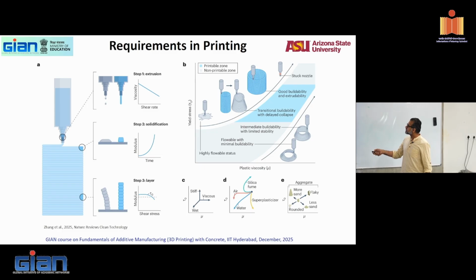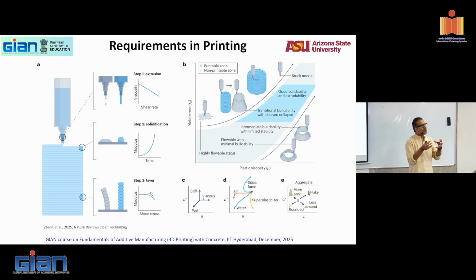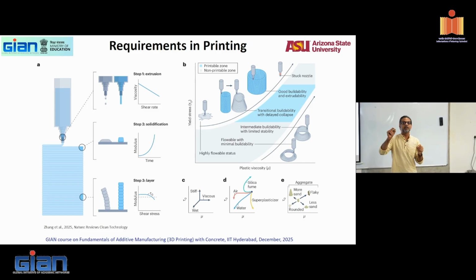Now, I can have the modulus gradually increase with time like that. Is it enough for me? I want it to be quickly increasing with time. So, here is a concept that we are connecting from everything that we have heard so far. If I want modulus to be quickly increasing with time, what is the best way to do it? If you are talking about cement hydration, I can make the modulus go up as the cement gets more and more hydrated. Does it make sense? I increase the hydration of cement, which means I have one particle of cement, infinite amount of water around it. As this particle of cement hydrates, my stiffness will increase, correct?